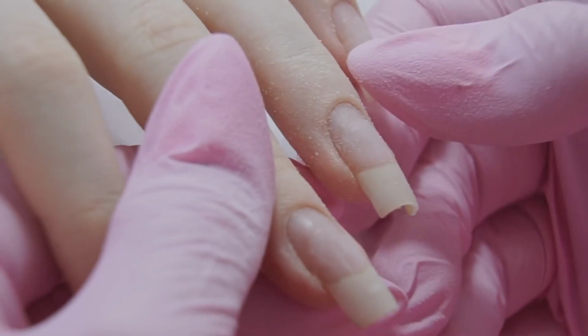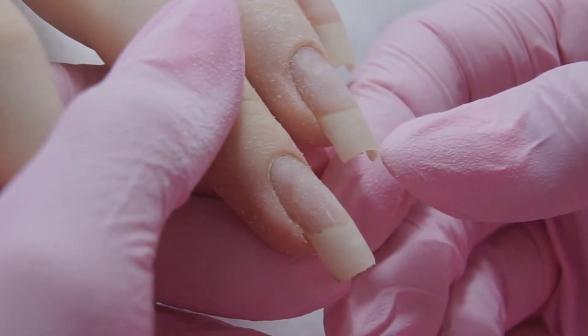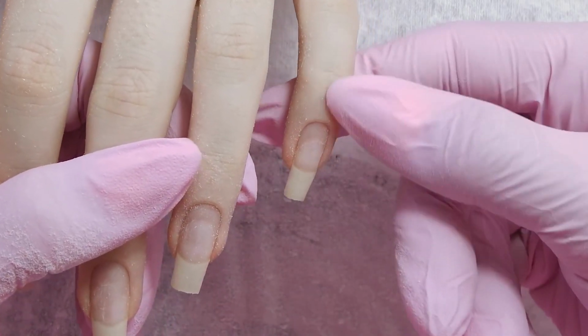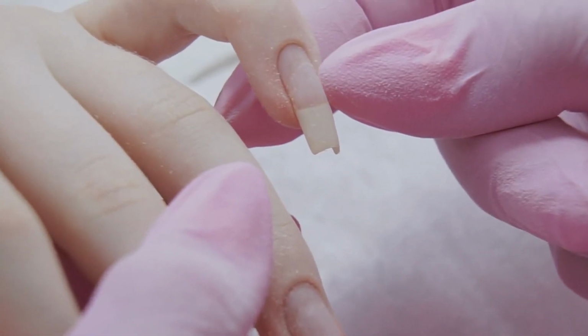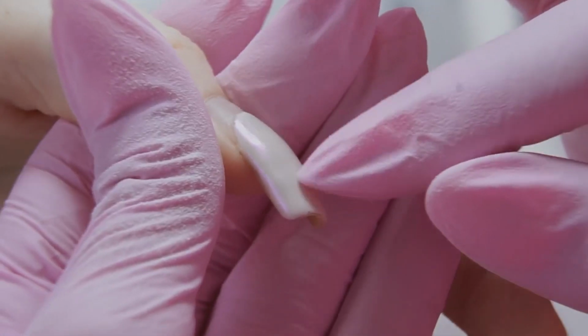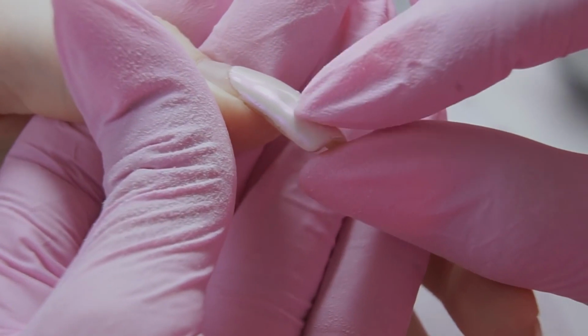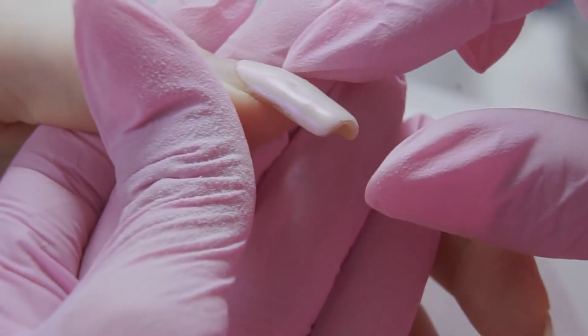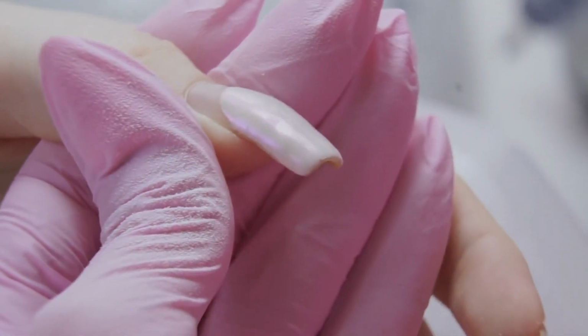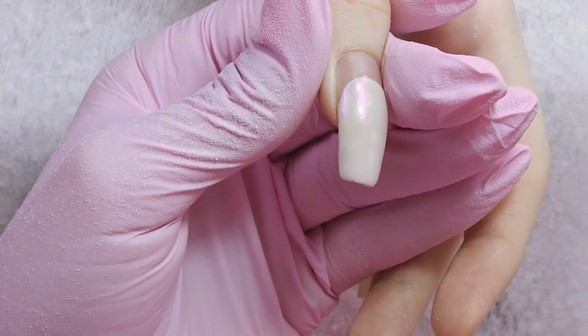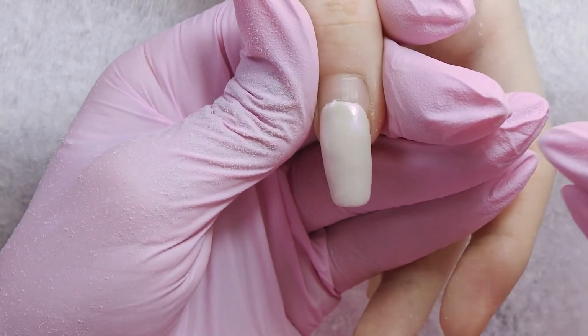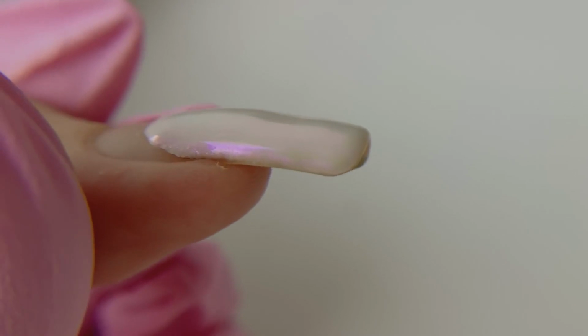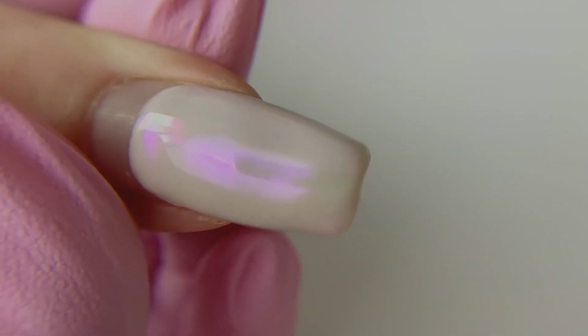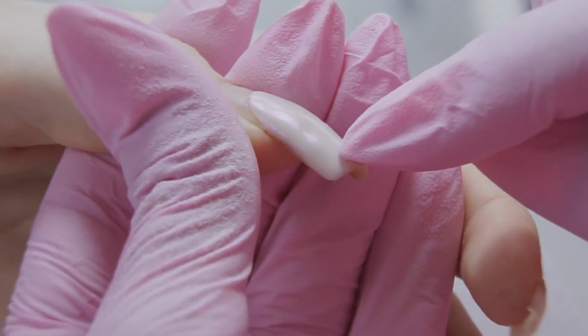I must admit that despite the fact that the base has been worn for a while, it holds up well, there are no liftings. On a thumb, we can see a material shrinkage, but I don't think that the nail tech made a mistake. It happened because of the nail growth and the pressure on the free edge. Gel polish stretches and sags over time, and such dips appear.